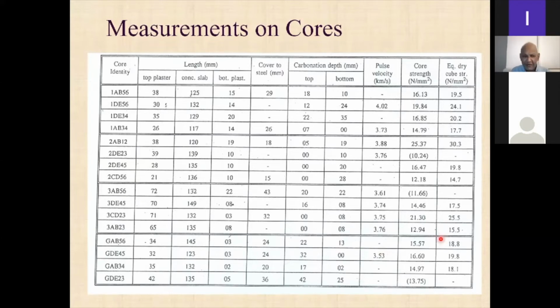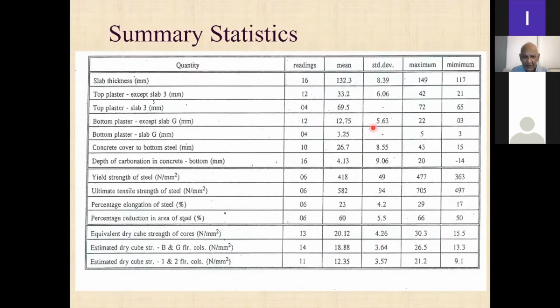So some of the statistics that we got, the mean and standard deviation for slab thickness, concrete cover, depth of carbonation, yield strength of the steel from the steel that was cut, percentage elongation and things like that. And then, using some of the methods available at that time of this new Eurocode, the estimated cube strength for the cores, and then this is for the columns. Now the columns, of course, I think we did not take cores. We used ultrasonic pulse velocity and correlated it with the cores that we got from the slabs.